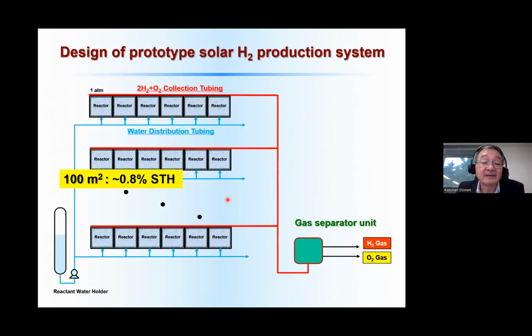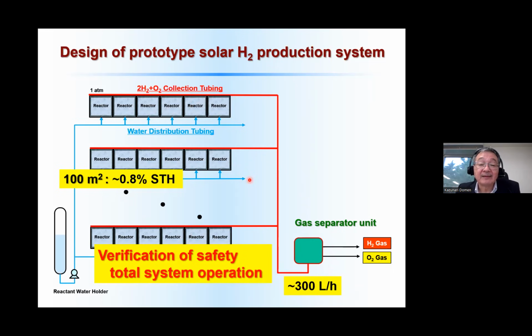Okay, so as I showed, we have constructed a 100 square meter light receiving area, and the solar to hydrogen energy conversion efficiency under the optimum condition was about 0.8%. The optimum rate of gas evolution was about 300 liters per hour. This is enough to check our gas separation systems. However, we need to examine more carefully the verification of safety and total system operation.